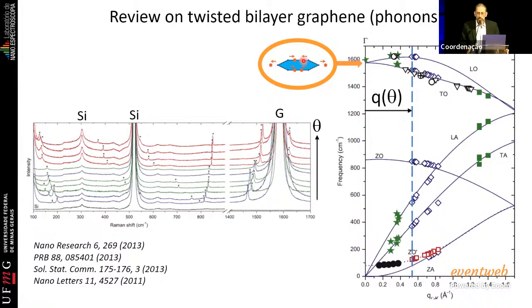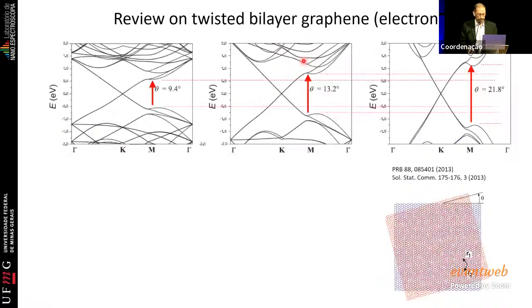And this is something very unusual and special, because if you want to map all the phonon states of any material, usually you need neutron scattering or X-ray scattering, because you need a very small wavelength so that you can probe these large Q vectors. But here you can do it with the trick, let's say, of twisted bilayer graphene.